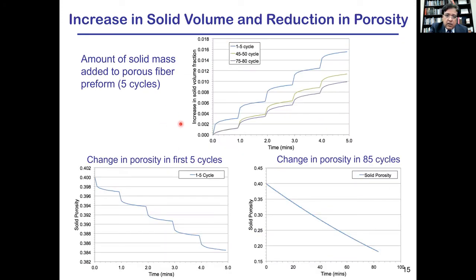continuous material where chemical reactions help increase the density of the material. Here is the increase in the solid volume as a function of the slurry infiltration cycle. In each cycle, as the particles come in, fresh slurry material laden with more particles arrives, so there is a rapid increase. Then as the particles get dropped, the rate of increase in the volume fraction of the solid decreases. Next, a fresh cycle is repeated. So this model can be used for slurry infiltration.